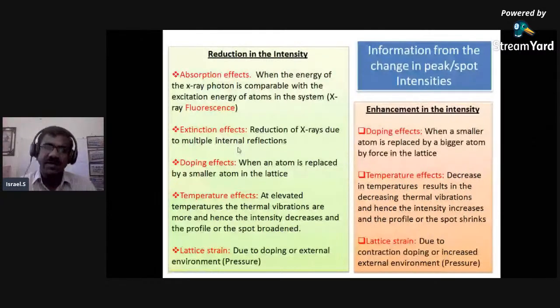Then there are doping effects. When an atom is replacing an atom of the same type, there is no problem. When the atom is replacing a smaller atom or a bigger atom, because of the lattice strain, when you are pushing a small atom into the system, the lattice shrinks. When you are pushing a larger atom, the lattice has to accommodate the larger atom. So there is a strain, there is a bend that takes place in a plane, and because of that, the reduction can occur.